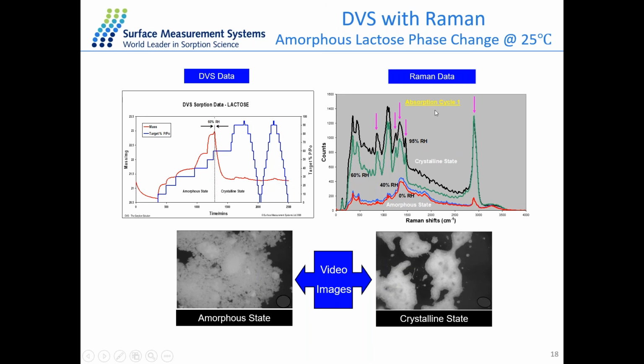And you see at the second cycle here, it's an irreversible phase change because you didn't see the same effect in the second cycle. And from the Raman data on the right-hand side, at lower humidity steps, there are quite broad peaks showing the amorphous state. And exactly above 60% RH, there are some new peaks showing up here, which indicates the crystalline state. So this Raman data is just confirming the DVS data that there is a phase change from amorphous to crystalline at 60% RH, just like the DVS data showing here. And the same as the video camera, you can see it from the image as well. So this combination gives a very good understanding about the material changes along with different humidity or different temperatures.